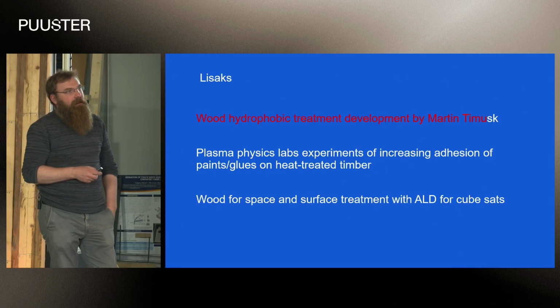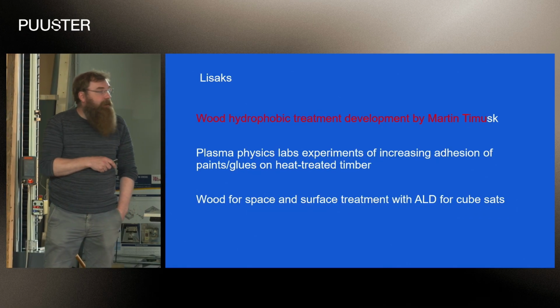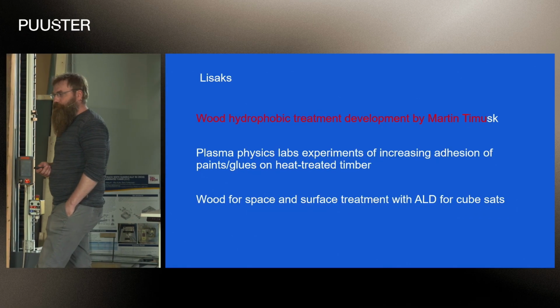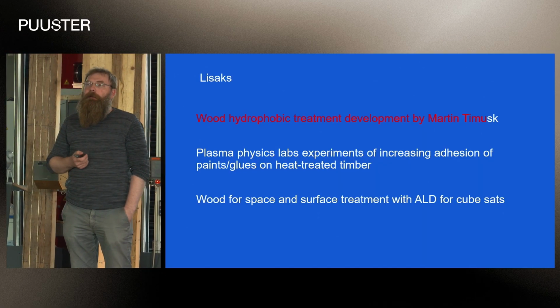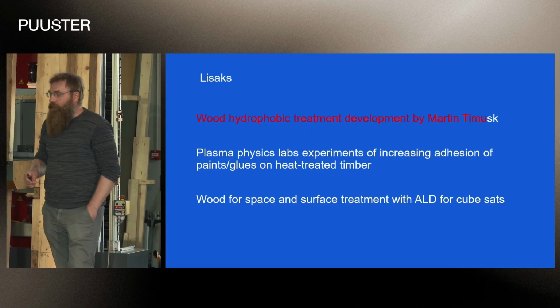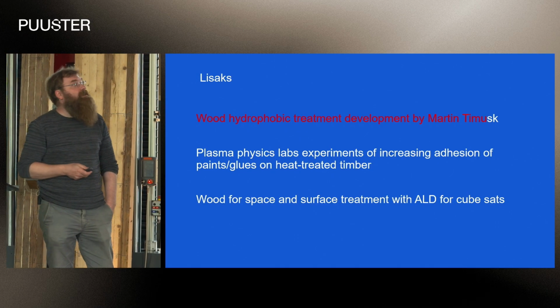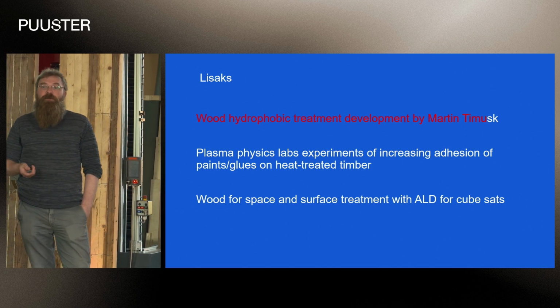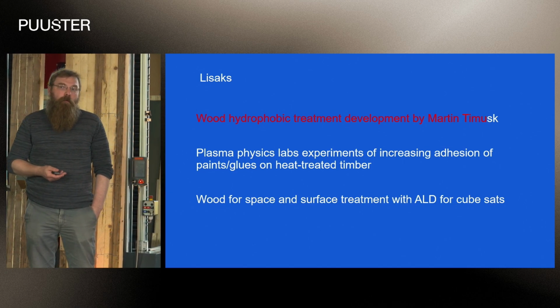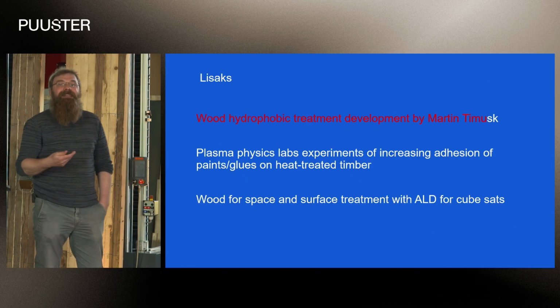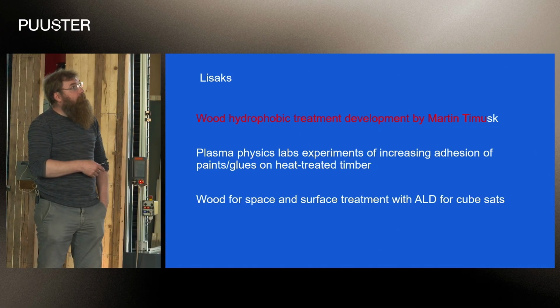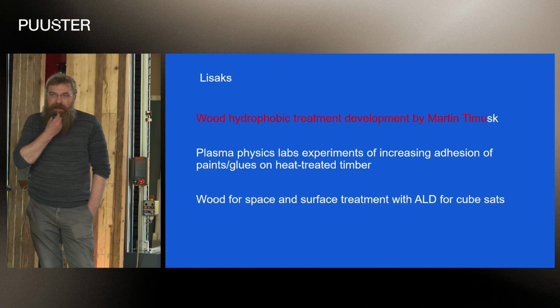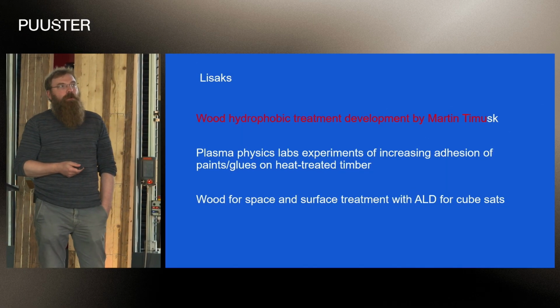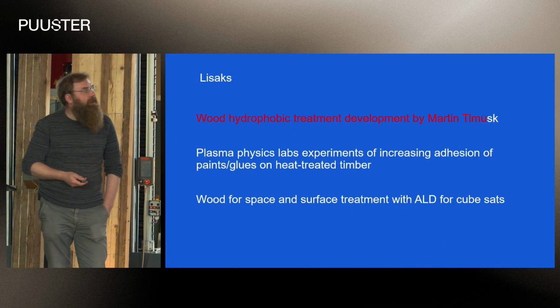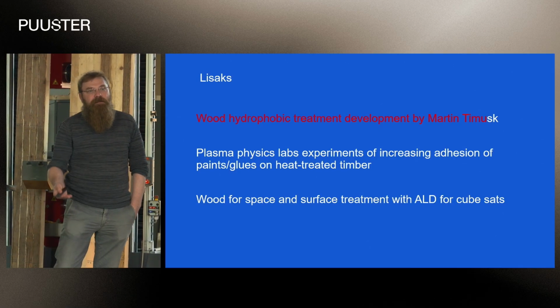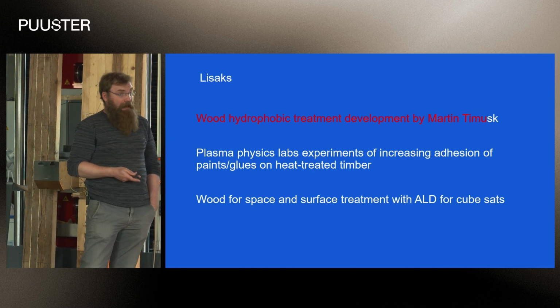Then some labs in our institute have done plasma research on wood. One of the main ideas here is that, for example, thermally treated wood, and probably also this densified wood, which is also thermally treated in some sense, they do not have a good adhesion with paints, glues, and one needs to increase the adhesion between the treatment layers and the wood itself. And here plasma treatment has been shown to mitigate some of the effects, increasing the adhesion in some cases. Now it depends on plasma type, the gas type that you use in plasma, and I don't have time to